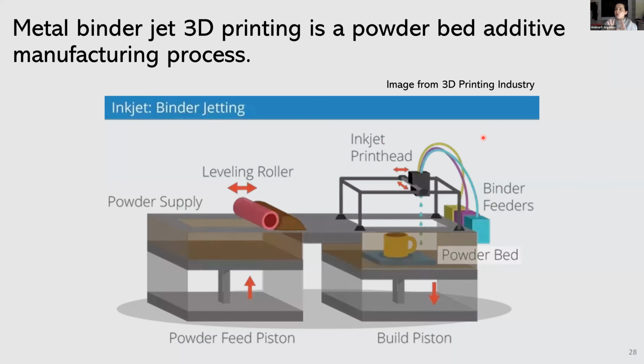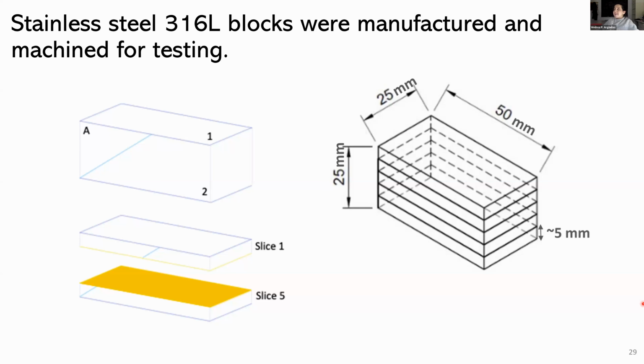So you burn off the binder and then you either infiltrate with a second material or just sinter the part itself. We've done analysis of both infiltrated samples and sintered samples. I'm only focusing on the sintered samples today, and particularly a sintered block of stainless steel 316.